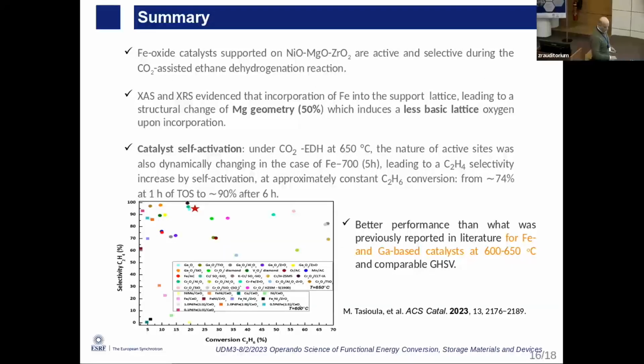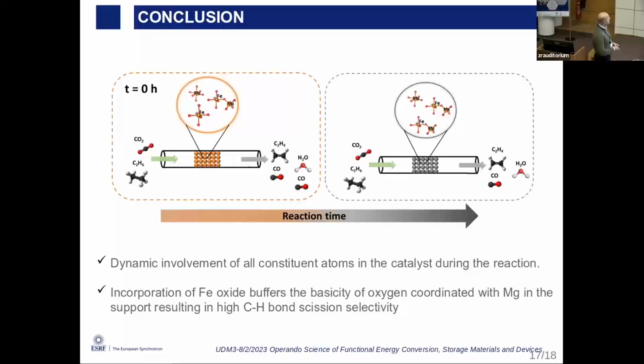So to conclude this work, we can say that the dynamic involvement of all constituent atoms in the catalyst happens during the reaction. And this is like the holy grail, if you want, of the catalyst. So we have to think about catalysts differently. We need to consider also the support, especially for this kind of reaction. And the incorporation of the iron oxide, that is another interesting point, buffers the basicity of the oxygen coordinated with magnesium in the support, resulting in high C-H bond scission selectivity.